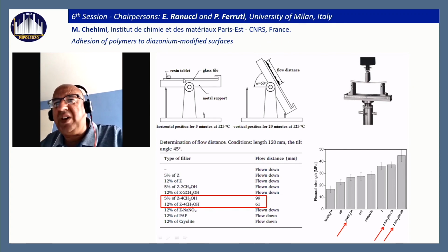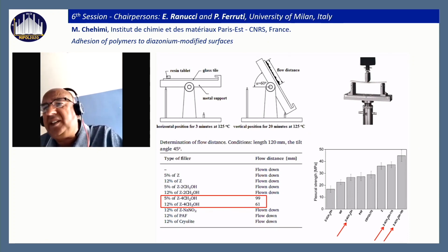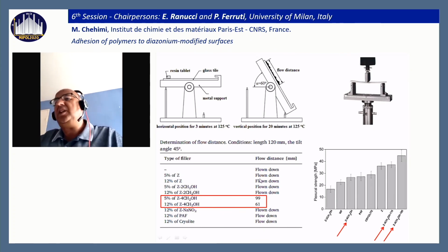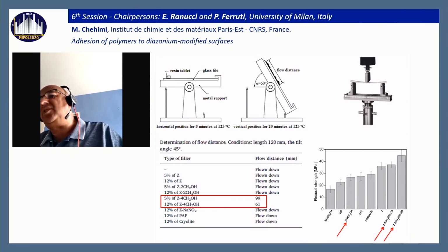For example, when we make the resin with Novolac filled with modified zeolite, and we tilt the plane here, we see that if there is no interaction or weak interaction between the modified zeolite and the Novolac, there is a complete flow down of the filled resin. But with the para position here, we have strong interaction between the Novolac and the modified zeolite, and we have only a small distance over which the resin is flowing, because we have the start of a cross-linking of the resin used to make the abrasive tool.